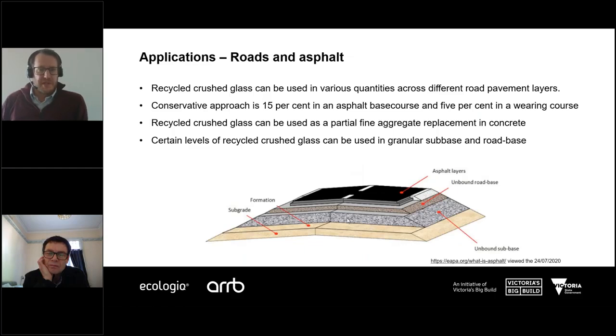So now I'm just going to talk a little bit about road structures and where we could potentially use our recycled crushed glass. The schematic at the bottom of the slide shows a typical pavement cross-section. What we're trying to do in our road pavement is protect the subgrade from the traffic loading. And in order to do that, we build up a structure with various layers, typically increasing in modulus as we go up through the layers.